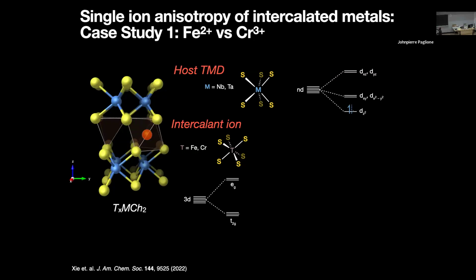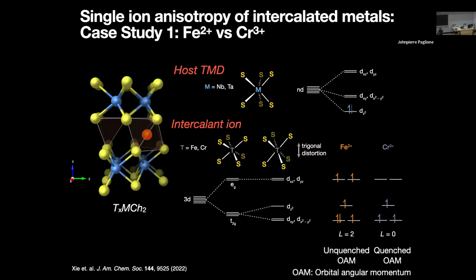And if you have a perfect octahedral coordination geometry, then what that's going to do is take your 3d orbitals and split them. Group theory gives you this result: it will split them into a triply degenerate and a doubly degenerate set, a T2g and an Eg set. But then in these materials, there's an additional trigonal distortion, right? So you take that perfect octahedron and you stretch it along the crystallographic c-axis of the material, and that is going to decrease the symmetry around that intercalant ion, taking it to D3d instead of octahedral.